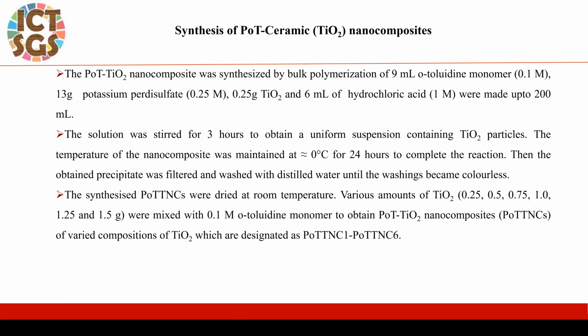Synthesis of PoT metal oxide nanocomposites. PoT metal oxide nanocomposite was synthesized by bulk polymerization of 9 ml orthotoluidine monomer and 13 gram potassium peroxydisulfate, 0.25 gram titania and 6 ml of hydrochloric acid were made up to 200 ml. The solution was stirred for 3 hours to obtain a uniform suspension containing titania particles. The temperature of the nanocomposites was maintained at 0 degrees Celsius for 24 hours to complete the reaction. Then the obtained precipitate was filtered and washed with distilled water until the washings became colorless. The synthesized PoT TNCs were dried at room temperature.